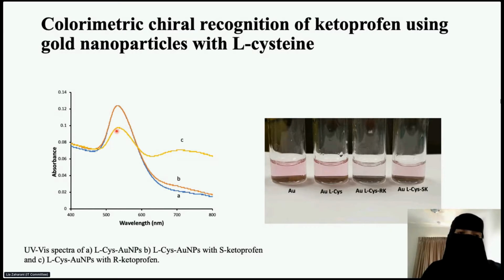However, when we introduce R-Ketoprofen, the peak at 536 decreases, and we have a new peak at 720. The existence of a new peak can lead to the interaction between R-Ketoprofen and L-Cysteine and the aggregation of the gold nanoparticle. So that means a selective response toward R-Ketoprofen, which was obvious in the color of the solution.